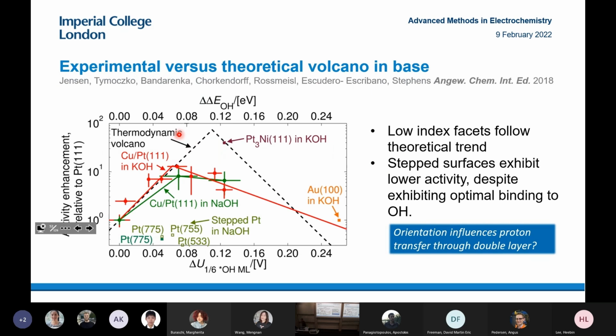So co-plotting this data, including both our own data and also data from platinum-3 nickel in KOH and gold in KOH, we see nice experimental volcanoes. So it suggests, at least for these low index facets, the facets which are not stepped, we see a good agreement between experiments and theory, and the Sabatier volcano exists. However, for stepped surfaces, in sodium hydroxide and potassium hydroxide here, they don't agree with the volcano model.